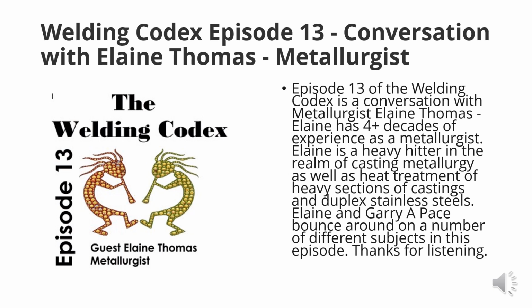Right, and then we're getting kind of the best of both worlds. We're getting a corrosion resistance that'll stand up to a brine or a saltwater situation, but we're also getting strength and more strength at an elevated temperature that we wouldn't be able to achieve with an austenitic or a super austenitic stainless steel. Well, it's not really used at elevated temperatures. It's usually used at 50 degrees centigrade and lower, more like earth temperatures. It's not really for anything high temperature. So that's kind of important too.